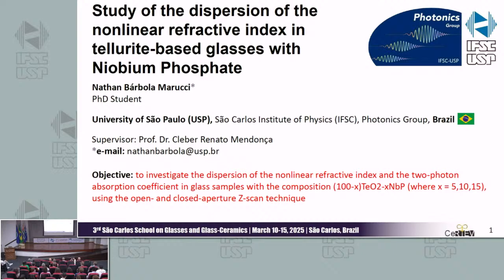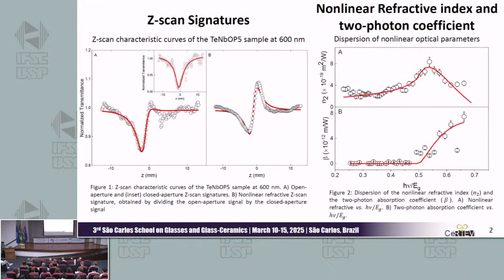In this school, I will present the dispersion of the nonlinear refractive index in tellurite-based glass with this composition. We conduct the nonlinear optical experiment using the open and closed aperture Z-scan technique. Here you have the nonlinear Z-scan signatures, and here we have the nonlinear refractive index and the two-photon absorption coefficient as a function of the photon energy.